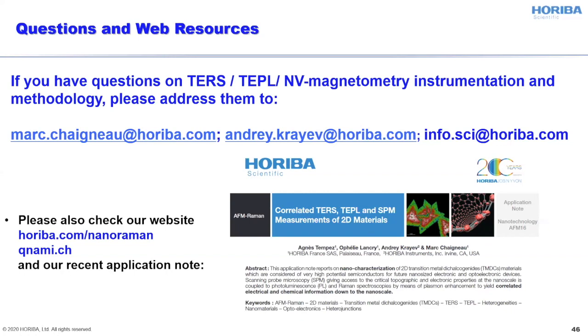So peak assignments in two-dimensional semiconductors, it's still a job that needs to be addressed by theoreticians, and I hope it will be done sooner or later. It's a challenging thing because it's a complex system with excitons playing an important role, and the mere density of the peaks in these materials complicates the picture quite dramatically, but it is important. Without understanding why we see those peaks and what those peaks mean, there will be no real progress in the characterization. But at this time, at least we are glad that there are some well-reproducible spectral signatures. And based on this reproducibility, we can start thinking about working with our theoretical partners on the interpretation of the nature of those peaks.